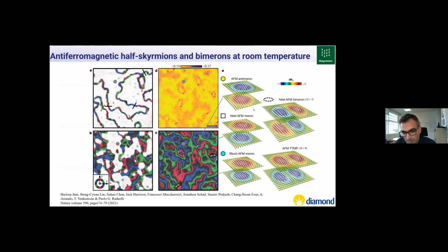That's the best way to describe it, where you have a topologically non-trivial structure, and they appear in pairs in the system, and they can be easily annihilated by a magnetic field or a hysteresis in temperature. And this can potentially store information at a very small scale. It's a very interesting system because Fe2O3 is relatively simple to make. So this is topology in real space, and something that we see a lot of examples of. This is done using photoemission electron microscopy with X-ray beams, but you can also start to look at this using coherent X-ray imaging, which is the next step, I think, in the journey with this material.